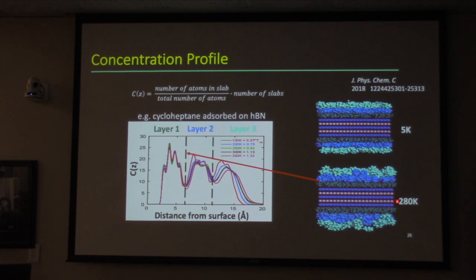These are some equilibrium snapshots. But what's really interesting is whether you're at 5K or 280K, the layer closest to the surface turns out to be stabilized. In the cases where the surface has some grip, it raises the melting temperature. Typically the melting temperature of a single layer of atoms at the interface is about 70% of the bulk triple point, so they all tend to melt at a lower temperature than they would in the bulk. In these cases, the melting temperature of the layer near the surface extends above the bulk temperature by 20 or 30%.